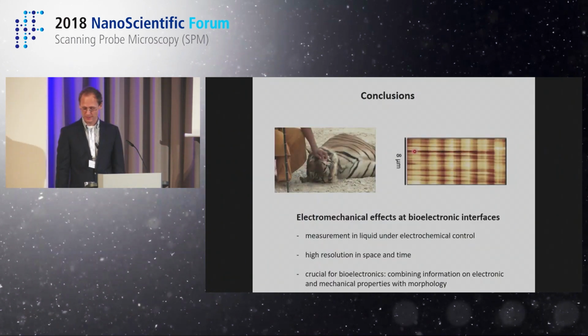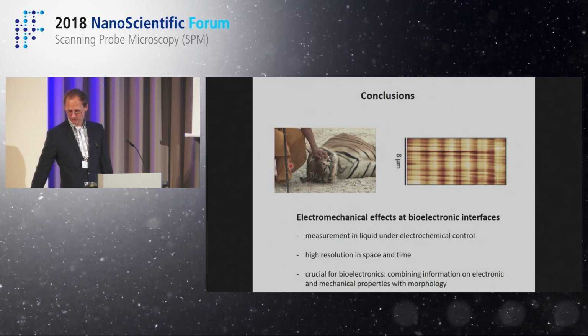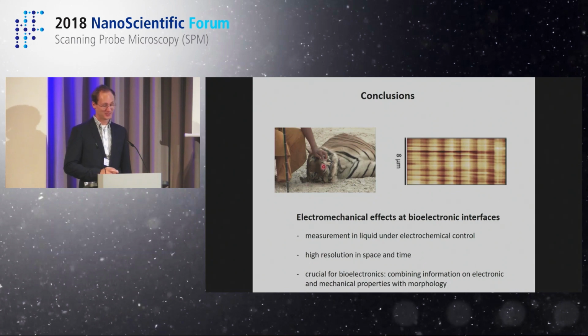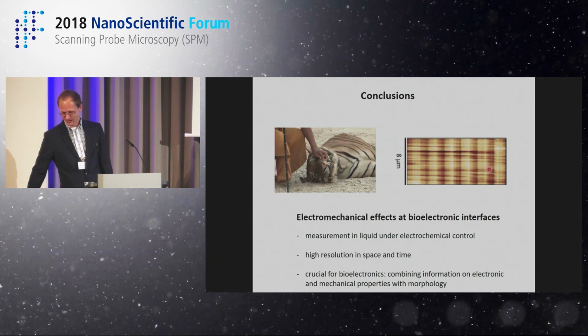Okay, regarding AFM, again, here are the conclusions. Touch your samples, takes the risk of also damaging them. I mean, you have to know actually what you're doing, like here with a tiger, and then you get much more knowledge about your materials and what is happening with respect to these bioelectronic interfaces. Of course, it's important to measure in liquid. If you probe morphology or properties in dry, you never have an idea; you have to go to the same conditions where the cells are doing their work. And that's also an electrochemical condition, so you need this electrochemical control.